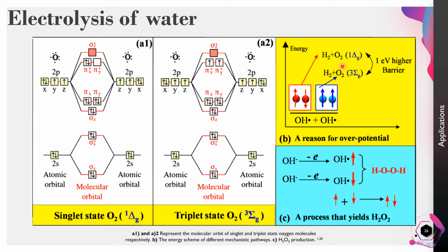However, due to the unpolarized electrons that usually come off of the electrodes in typical electrolysis, you get a mixture of both. However, if you polarize the electron beams using chiral compounds, you're able to select for one spin over the other, and this allows for a reduction in the potential difference needed to create the triplet oxygen. And it significantly reduces the need for overpotential.